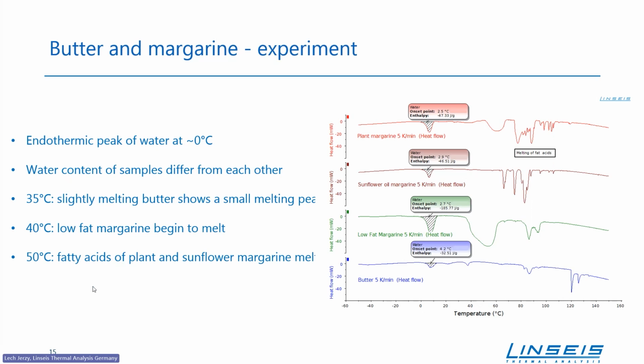As you can see, the first peaks at or close to 0 Celsius degrees are the result of water melting. Afterwards, the result of heating are endothermal peaks, coming from melting of different fats. Different types of fats give a different image of overlapping peaks between 80 and up to 140. So our mixture of fats was melting in this case, and in different temperature regions, we observe the melting of different ingredients in this mixture.